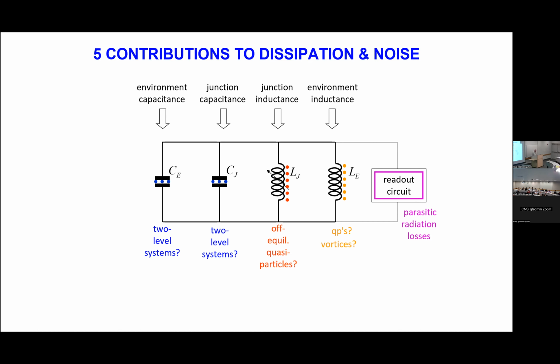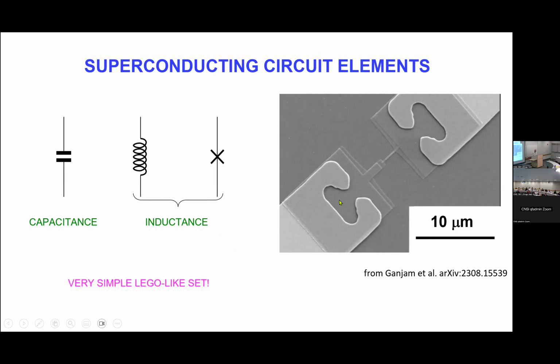But even leaving materials aside, you have essentially five things that you have to do correctly. First of all, you have to design the circuit so that you don't have radiation, you don't have dissipation to other electromagnetic modes. So there's microwave engineering involved, and you need to do this part correctly. In superconductors, you have vortices. For instance, in these big blocks of superconductors, you can have vortices. In fact, it is believed that this C shape has a good effect in the management of vortices. If you would have a vortex, let's say in here, it would be confined by this C shape, and it would not move.